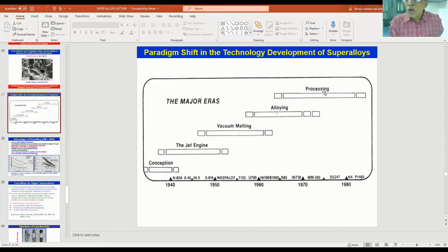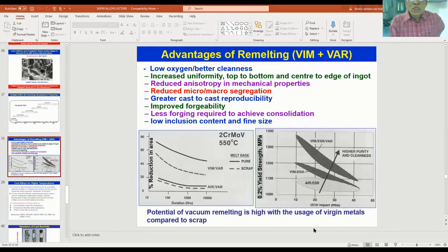Certain times, if you want to have very high performance in the superalloys, you have to use the triple melting process: vacuum induction melting followed by vacuum arc remelting, or vacuum induction melting followed by electroslag refining followed by vacuum arc remelting. You can see here what is the advantage of vacuum induction melting and vacuum arc remelting. They have low oxygen and better cleanliness when you apply these two processes together, one after the other.